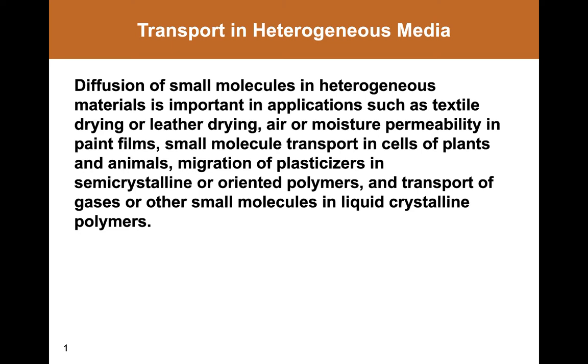And the basic idea is that many interesting nanomaterials are not suitable, often for mechanical reasons, of being fabricated by themselves into membranes. However, they may have very interesting transport properties. On the other hand, polymers are easily fabricated into membranes, at least a lot of polymers are, but may not have the same properties as the nanomaterials of interest. And so there's been a lot of study aimed at combining nanomaterials with polymers to make composite materials that have better transport properties than polymers alone, and have better mechanical and processing properties than the nanomaterials themselves.